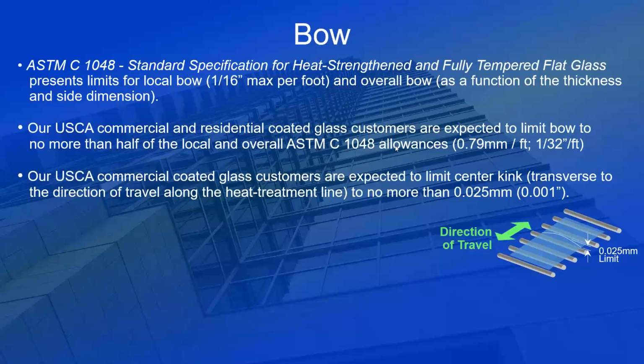There's also what's known as bow and warp. The standard specification for heat strengthened and fully tempered glass presents limits for local bow and overall bow. In the US and Canada, our commercial and residential coated glass customers are expected to limit bow to no more than half of ASTM C1048, so approximately 0.79 millimeters or 1/32 of an inch per foot. And as far as center kink goes, we prefer that it be limited to no more than 0.001 inch per foot.